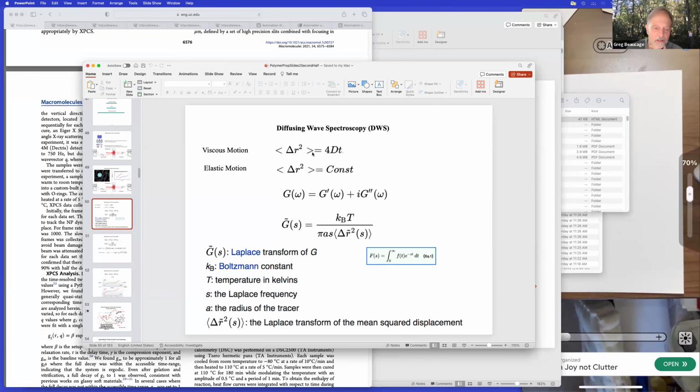So the gamma in the DWS thing, you're measuring this R squared. So basically, by measuring gamma, you're getting R squared, and R squared is composed of a real and imaginary component. And if you do a Laplace transform, which is a sum of all these exponential decays, then you can iron out the complex modulus, and omega frequency over the modulus gives you the complex viscosity. So you can get the complex viscosity from this measurement.